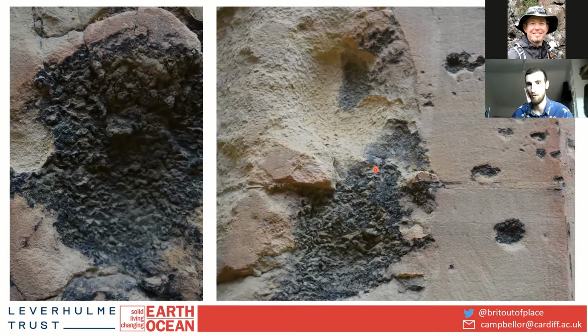And eventually this crust becomes heavier than that bond to the rock can cope with, and these crusts fall away. So they're very delicate. And so this crater, you can see here, all of this material has recently come loose. And again, here, this section has come loose. And now this bare stone is able to start reacting with the atmosphere again and with moisture, and deposits will presumably begin to grow here. And over time, this cycle continues the progressive deterioration of the stonework.